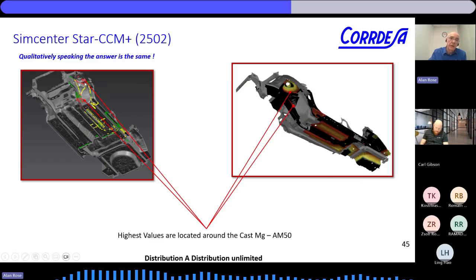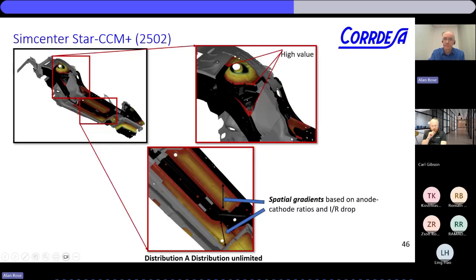So we've got risk on the left and the deep dive, the actual corrosion rate map, on the right. And it could be higher or lower because now we're capturing the actual geometry. So anode cathode area ratio of 1, it's not an assumption anymore. We have that geometry information.